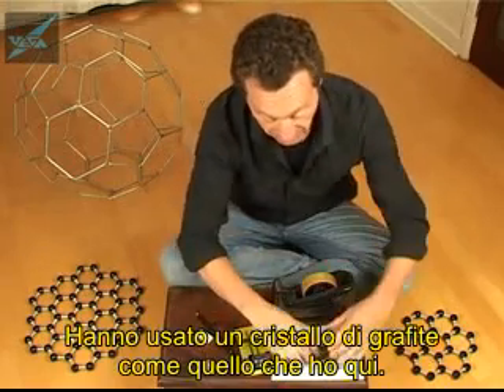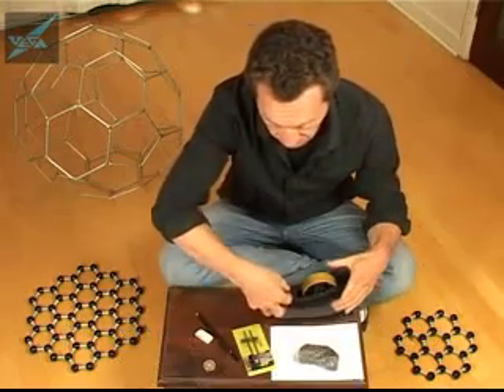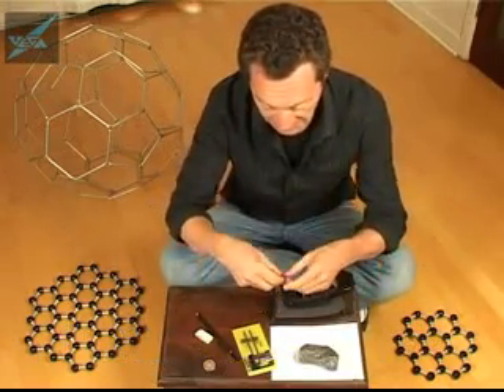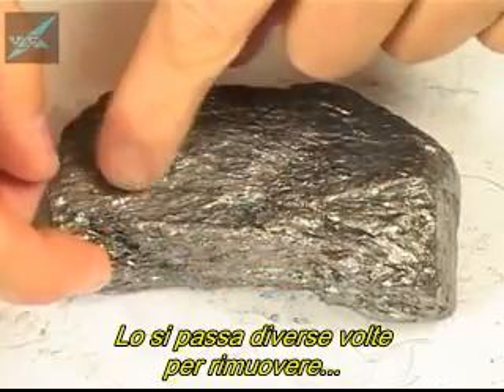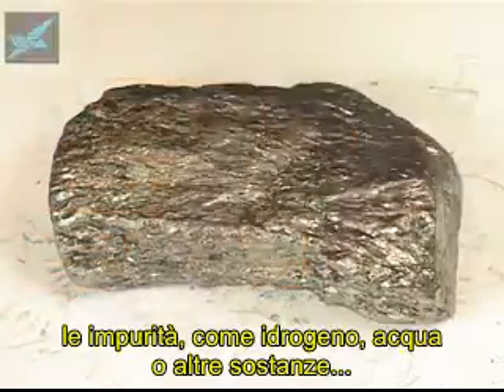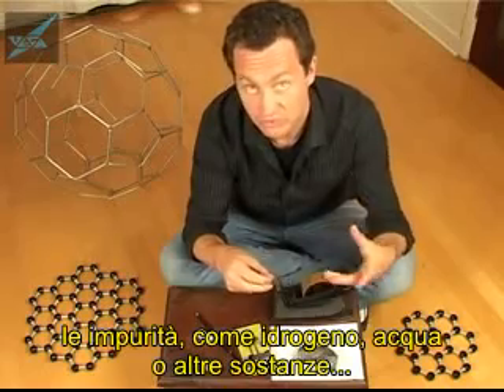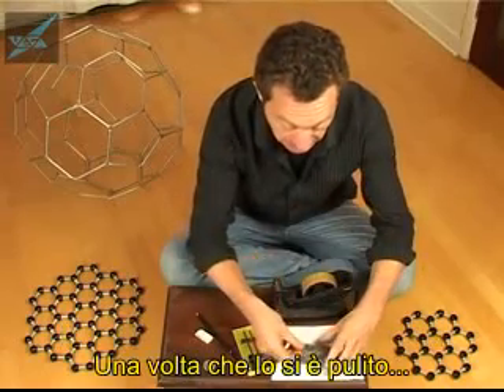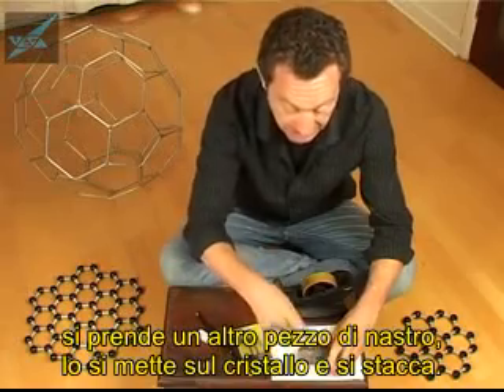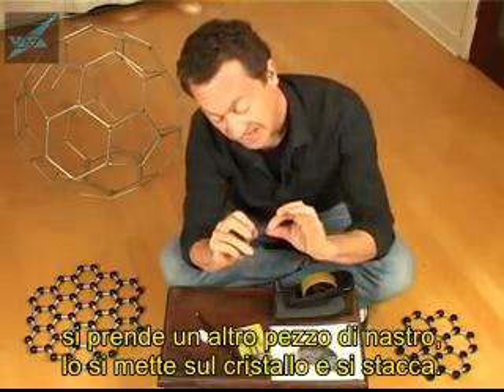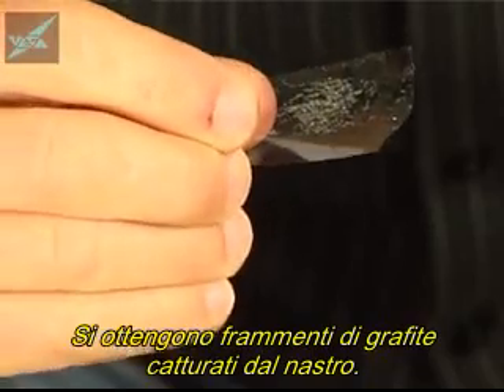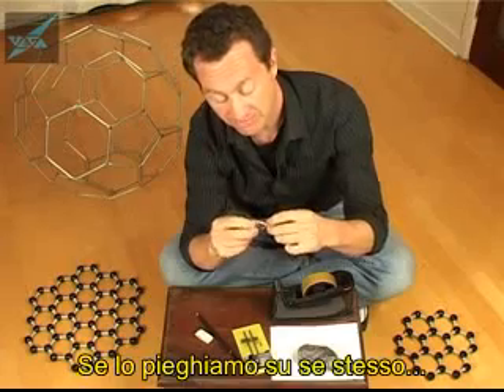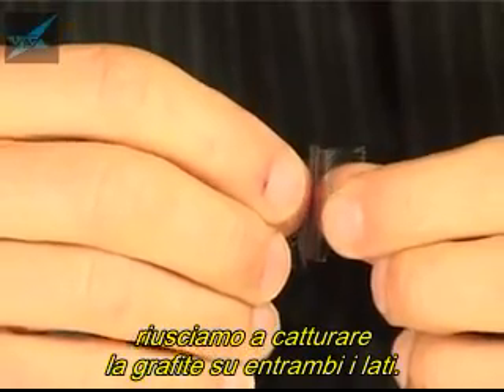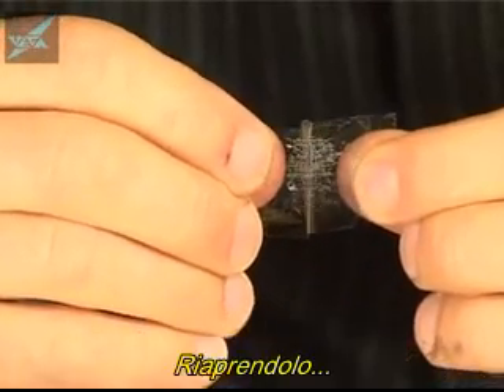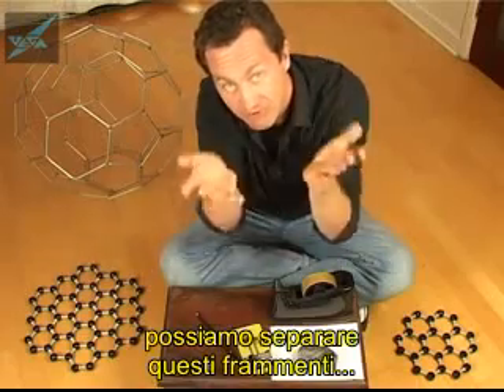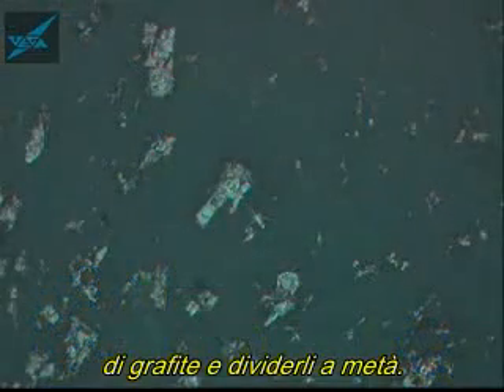What they did was they got a crystal of graphite, I've got one here, and with a bit of tape, you put that on the crystal, and actually you do this a few times to remove the impurities. There might be hydrogen and water and all sorts of stuff on the surface of the graphite. But once you've done that and you've cleaned it up, you take a fresh piece, put it on the crystal and pull it out. And actually what you've got is fragments of graphite picked up by the tape. Now if I bend this over, we can then capture the graphite on both sides, and as we pull it back again, we can separate out these fragments of graphite and split them in half.